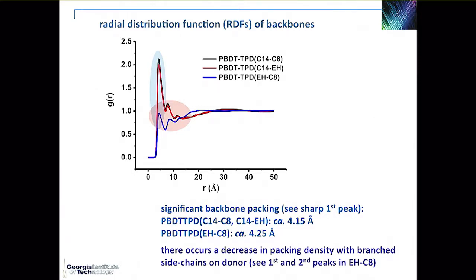But we looked at the radial distribution functions. That's basically taking a conjugated polymer segment on one chain and looking at where are similar segments nearby. So that gives you indeed a very good idea of how the backbones want to stack one with respect to another. And so the very sharp peak that you find in all cases, all 3 polymers, at 4 angstrom tells you that you have very significant backbone packing, but that there occurs a decrease in the packing density when you have branch side chains on the donor moiety, the electron-rich moiety.